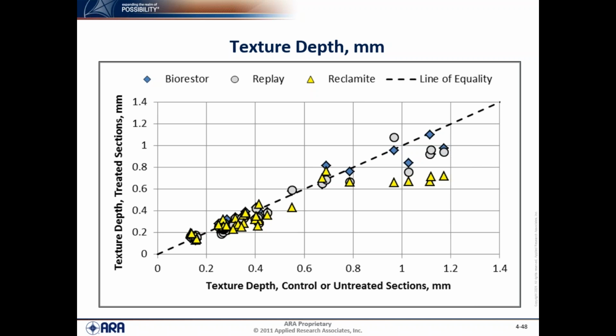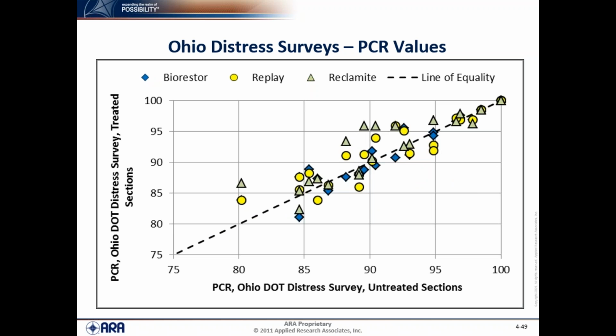Initially, after construction, you can see the data along the line of equality, which we kind of expect, but then over time you start seeing a little deviation from the control section. In other words, the texture depth of the treated section is consistently a little bit lower than for the control section, as shown here for the higher texture depths. So we're starting to see a little bit of difference within the 4-year monitoring period.